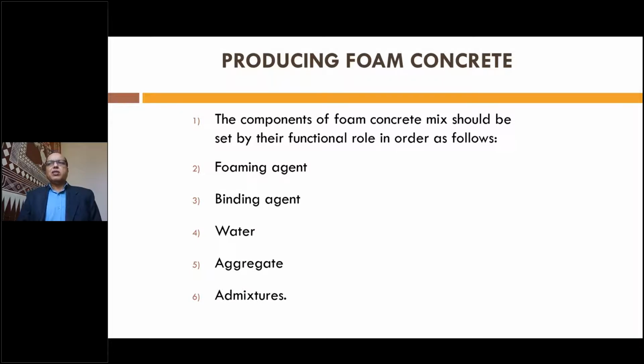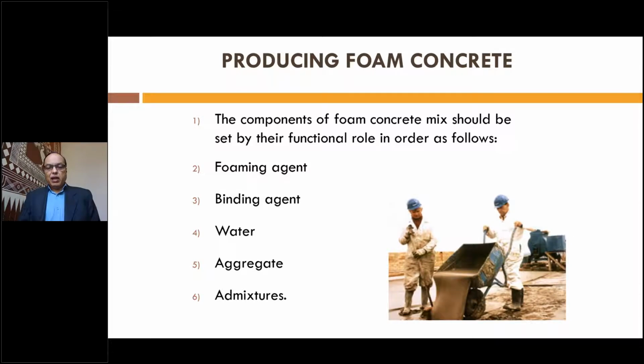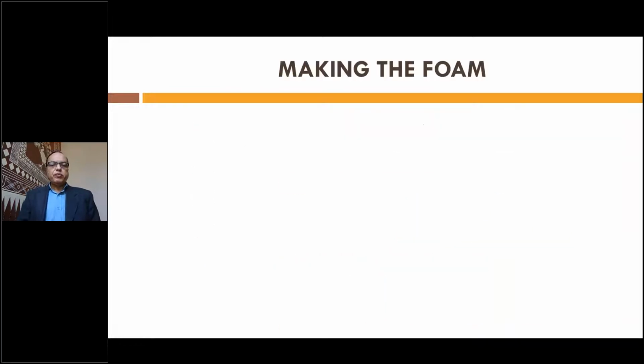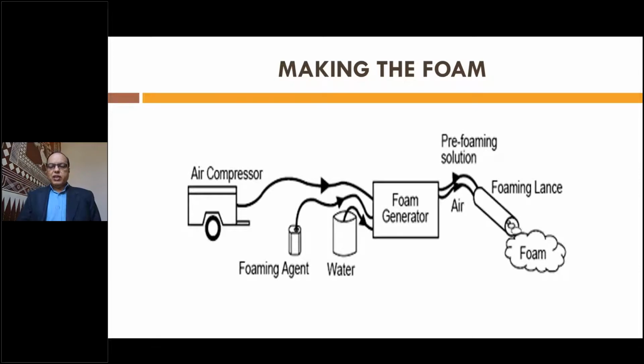We also make use of certain admixtures so that you can keep the water cement ratio as low as possible, but still the flow would be high because of the foaming agents. You can see in this photo, he is trying to pour out that concrete. You can see how it is pouring out, like liquid or like a foam. Making the foam is not a very difficult thing to do. You have the foaming agent and water that gets into the foam generator, and through an air compressor, the whole thing is mixed and a pre-foaming solution is formed. And from that pre-foaming solution, foam comes out, and that is mixed with concrete to make it foam concrete.